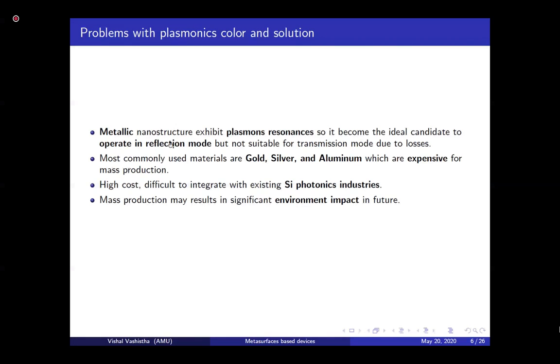Here I want to point out a few problems. First, metallic nano antennas operate via plasmon resonance and are very good in reflection mode, but not suitable for transmission mode — when light passes through the metal, a lot is scattered randomly and some energy is absorbed by the metal nanostructure itself, resulting in extremely low efficiency, especially at optical frequencies. Additionally, these metals — gold, silver, aluminum — are expensive. They are also difficult to fabricate with silicon photonics industry processes since CMOS devices are based on silicon, and they could have significant environmental impact.